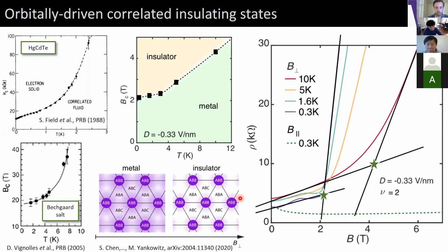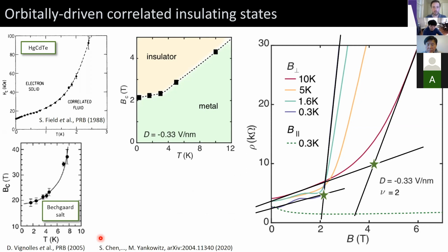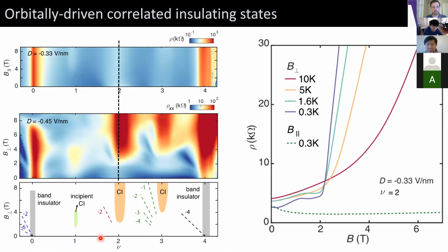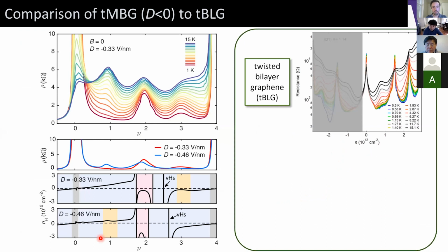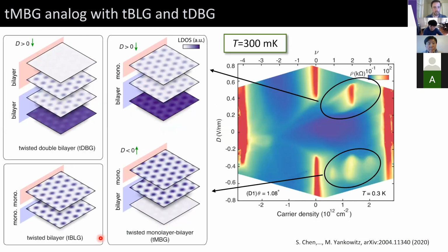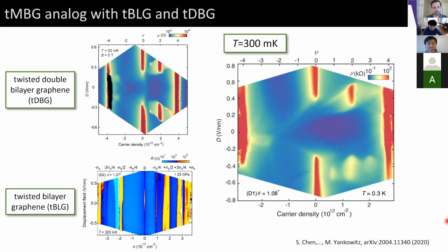And so we can assemble this sort of cartoon of what the local density of states roughly looks like, inferred from this behavior. So basically, I'm showing you now an average over all three layers. This is not a calculation, it's just a cartoon schematic, where the local density of states is localized around these ABB stack sites, but not very strongly at low magnetic field. And essentially that may be because we have an extra layer of weakly charged monolayer graphene in this configuration that could be serving to screen interactions in the active layers at the twisted interface.